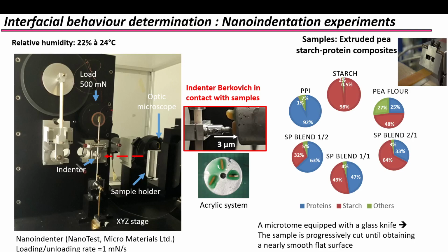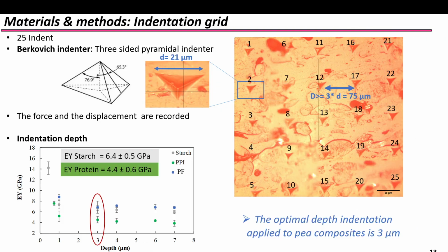The surface finishing was a critical issue to solve because of the sensitivity of the results to the surfacing of the samples. So these are some of the grids of indents that we achieved using a Berkovich-like indenter. We succeeded in doing a mapping through the entire composite, and it shows that depending on the depth of penetration of the indenter, you could get quite varied results. So we used a large depth profiling from 1 up to 7 micrometers,